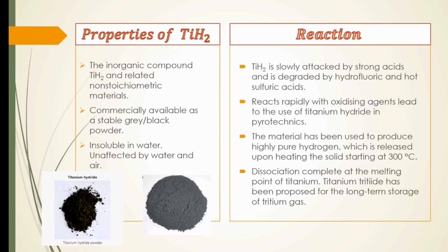It reacts rapidly with oxidizing agents, which led to the use of titanium hydride in pyrotechnics. The material has been used to produce highly pure hydrogen, which is released upon heating the solid starting at 300 degrees Celsius. The dissociation is complete at the melting point of titanium. Titanium tritide has been proposed for the long-term storage of tritium gas.